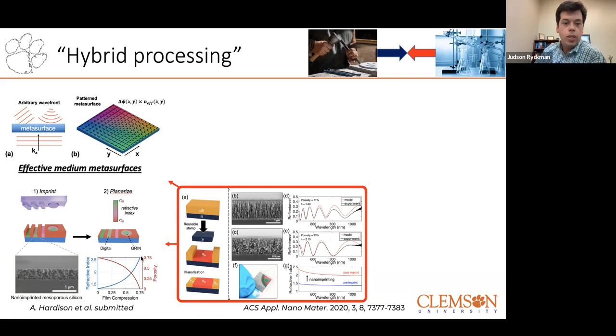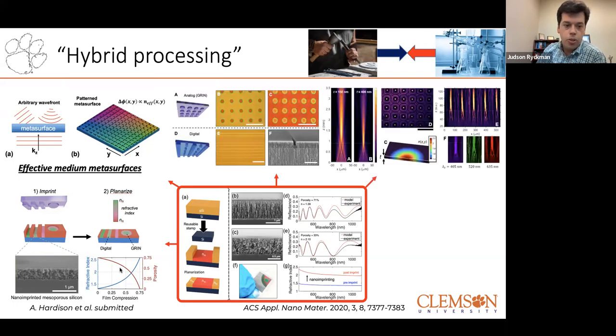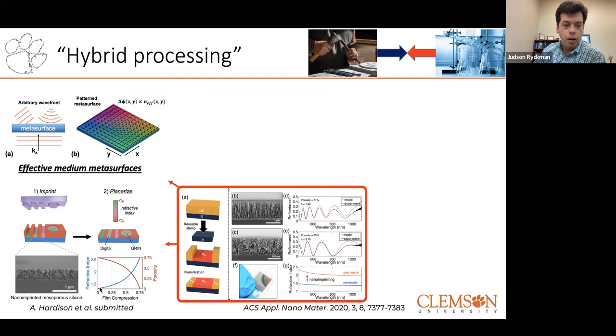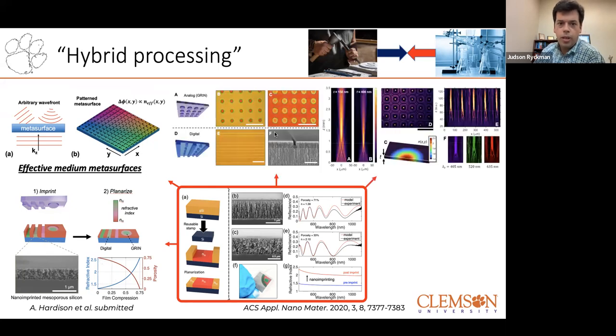So we can get up to about 2.6 because there's a sizable surface area of SiO2. But even then, our refractive index dynamic range is quite nice. It's over 1 RIU. And so we've also demonstrated some gradient index structures. So we'll planarize these films, and we've demonstrated some micro lenses based on porous silicon to do some wavefront shaping. So this is sort of our first demo, if you will, of an experimental effective medium metasurface.